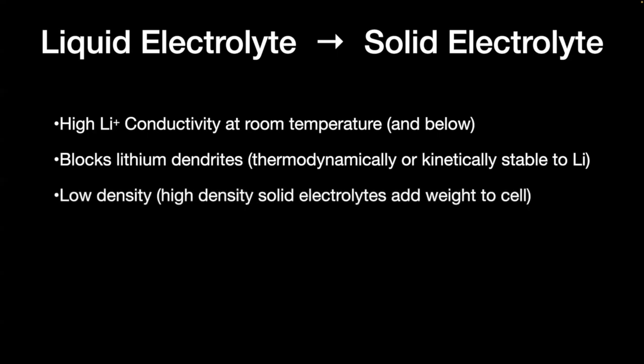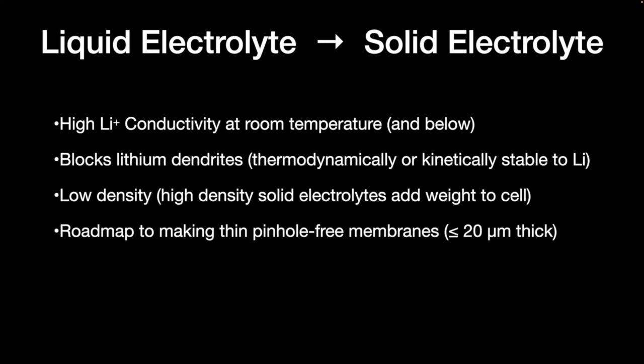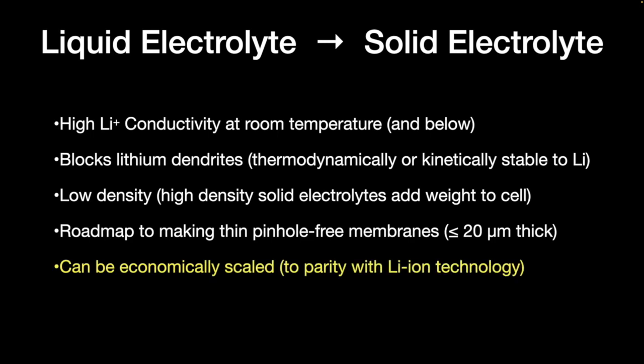You would prefer low density for your materials. Why? Because these are passive. The liquid electrolyte doesn't contribute energy to the cell, right? It's a passive component. So you don't want it to be heavy because that's going to add weight to the cell. So the lower the density of the electrolyte, the better off you are. And you need a roadmap to going thin because if you look at modern lithium ion cells, those membranes that separate positive and negative electrodes are pretty thin. They're certainly less than 20, and in many cases less than 10 microns. So you cannot be putting a thick membrane in here and hope to achieve record-breaking energy densities. And then lastly, but not leastly, if these technologies are going to end up in electric vehicles, there has to be at least a path to get to parity with lithium ion. So how do we do that?